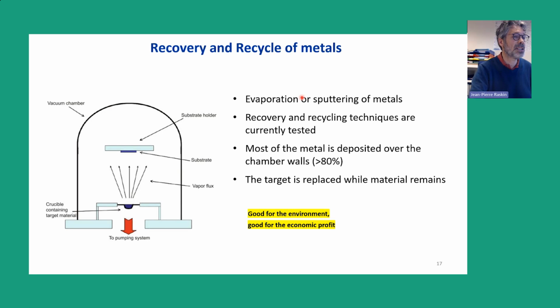And this is the reason it is still in place in many of those foundries, because you have to know that when you deposit thin films, for example by evaporation or by sputtering, most of the metal is deposited over the chamber walls. Depending on the process method, over 80% of the metal is really covering the walls and not really the substrate, the wafer, the target, basically. And this is a really important part of the material that can be recovered if they use the correct technique to recover the material.